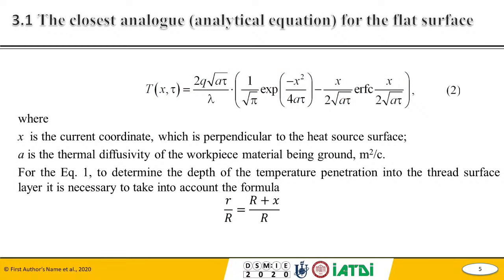This is the closest analog with the flat surface. You can see this equation on slide number 5. X is the current coordinate, which is perpendicular to the heat surface. A is the thermal diffusivity of the workpiece material being ground. For equation 1, to determine the depth of the temperature penetration into the thread surface layer, it's necessary to take into account the formula.